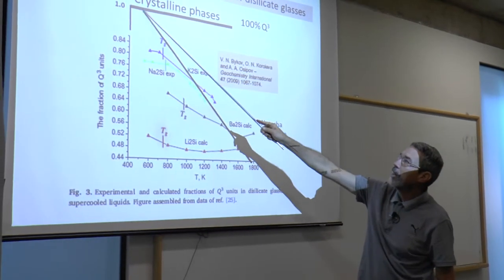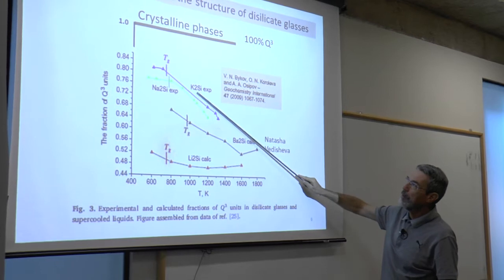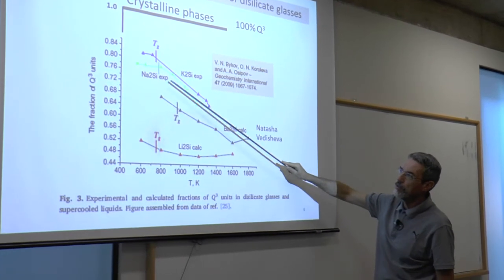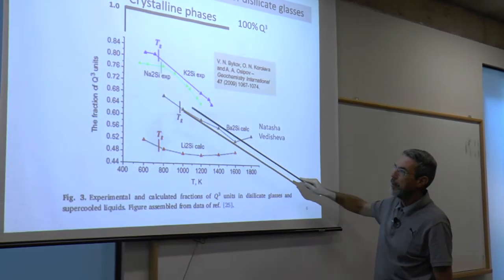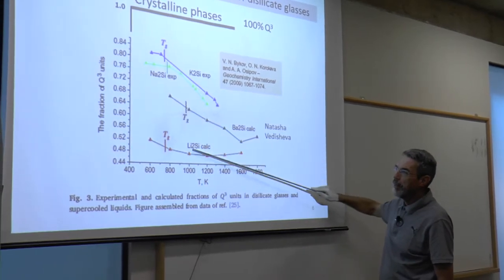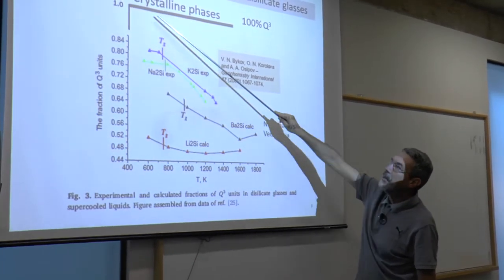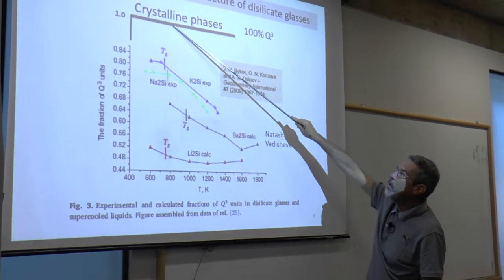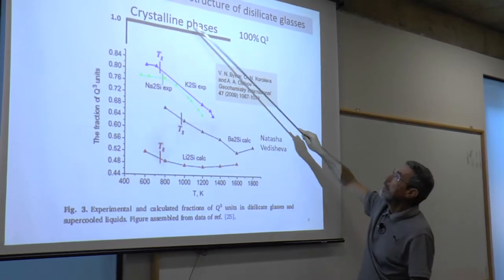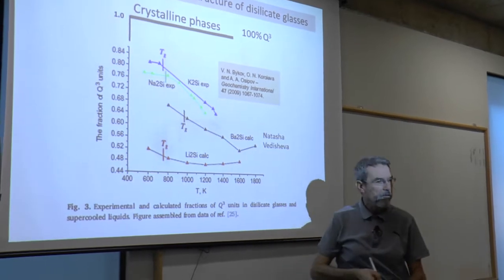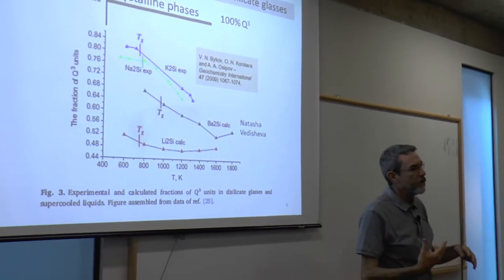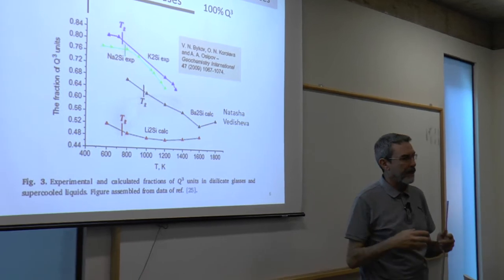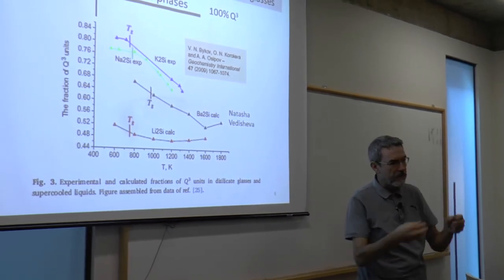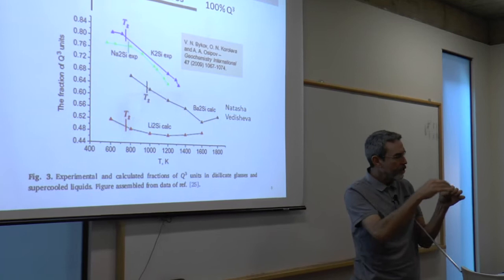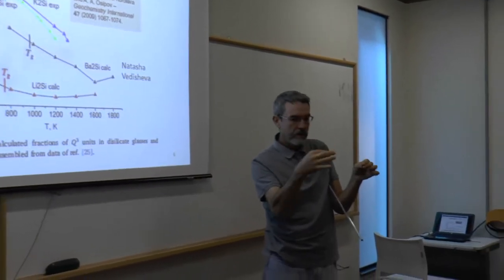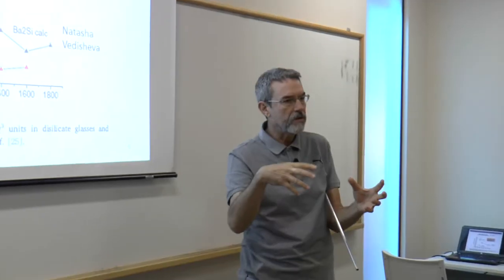If you look at the crystalline phases, for instance, this is potassium disilicate, sodium disilicate, barium disilicate, lithium disilicate. Their crystalline phases all have 100% Q3. The structures of these disilicates are known by X-ray diffraction methods, and all tetrahedra share 3 corners. 3 corners are shared in a 3-dimensional network.